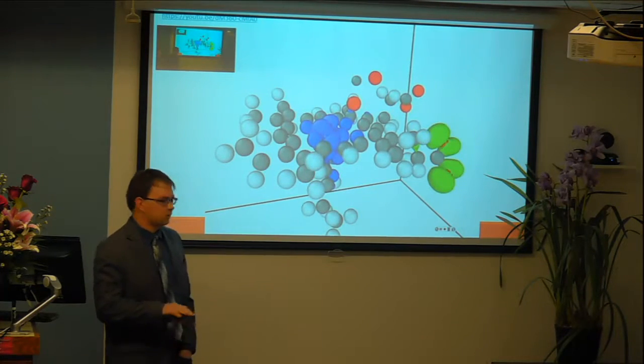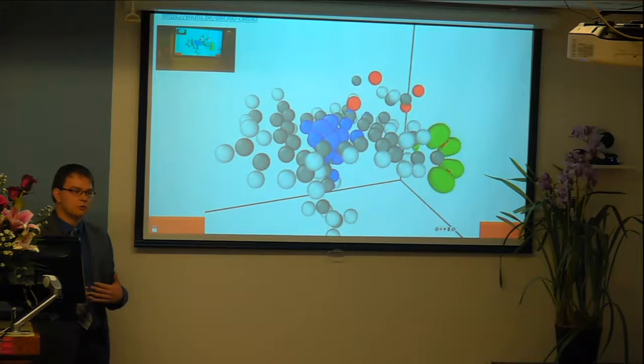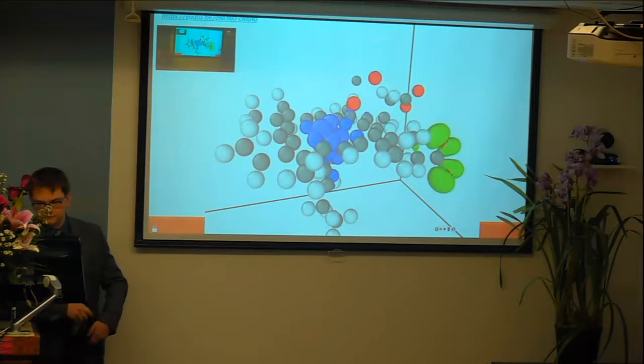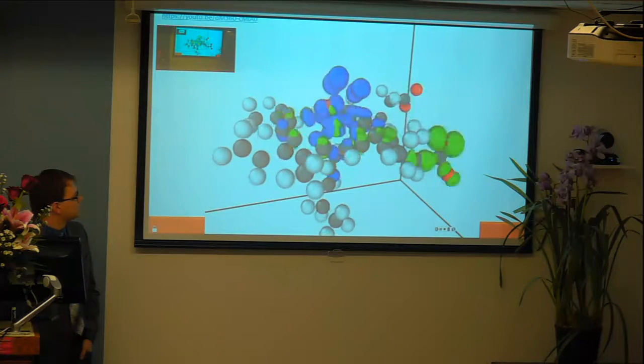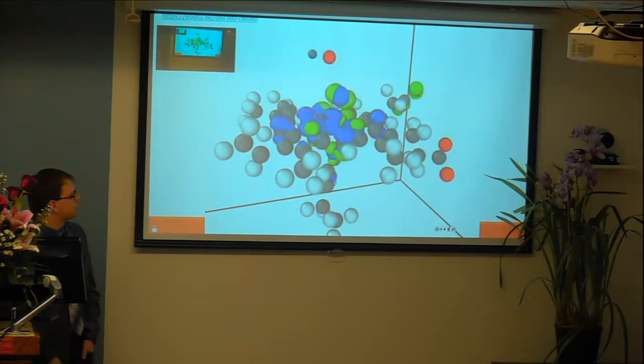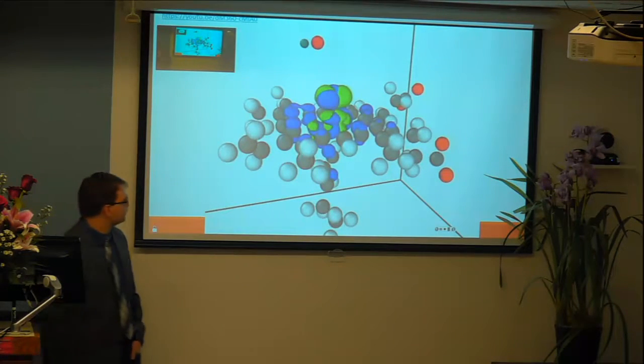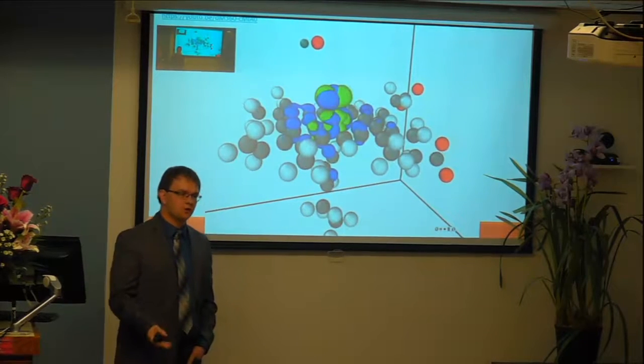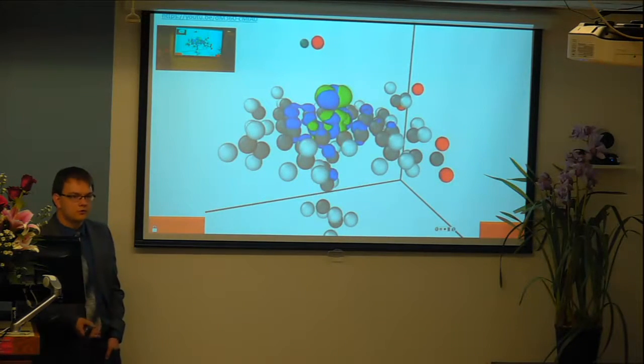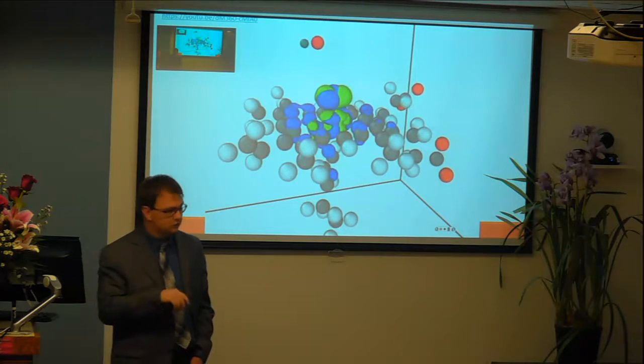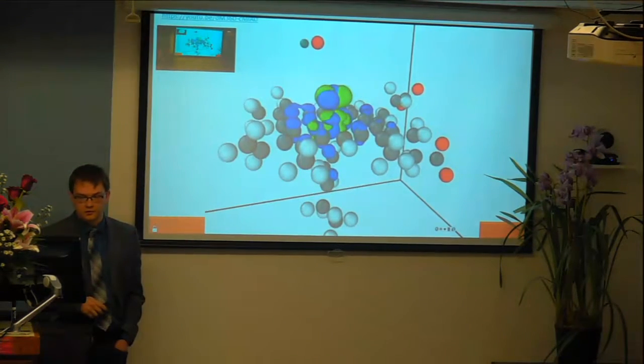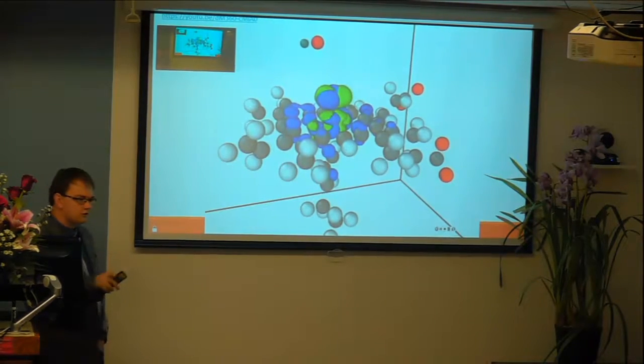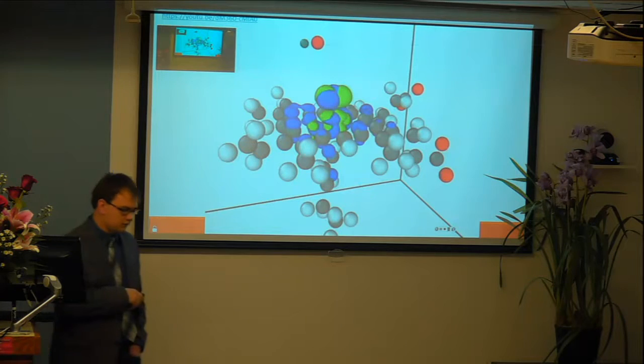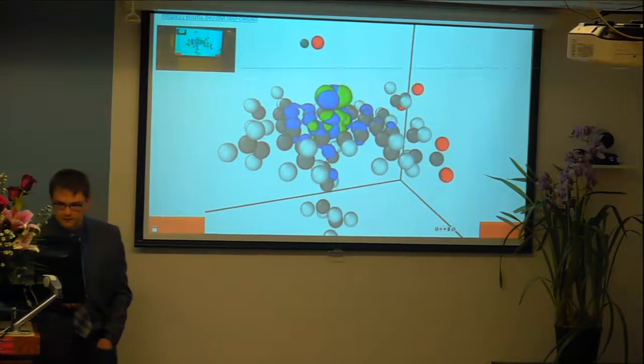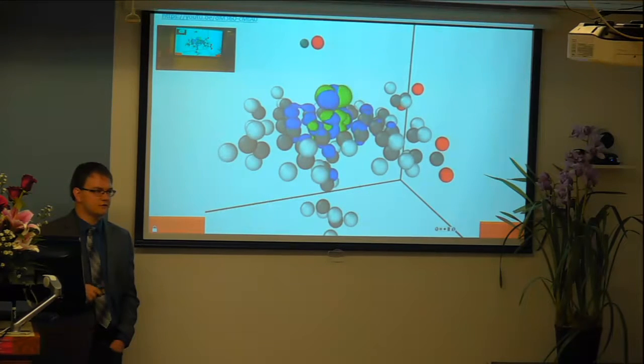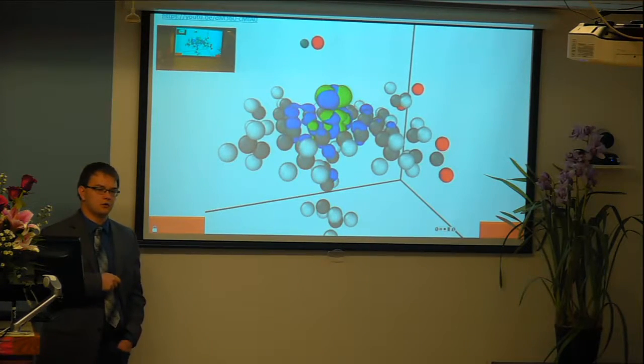And so here is a very preliminary result of, say, HOMO and LUMO orbitals as a progression of time. Of course this is very staggered because I only took every 10 steps. I calculated the electronic structure and computed the charge density. I can make this much smoother if I was to look at every step in the molecular dynamics. It's interesting because some of the charge densities look very nice, but they jump very quickly over a 10-step region. So this is really not that informational if I take that many steps.